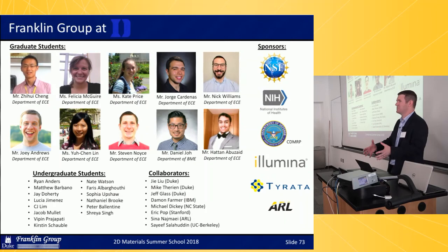And we're realistic enough in silicon to say, you know what, our devices are so small now, we can't dope the channel anymore, because 10 to the 18 dopant concentration would be 3 atoms in my channel, and I can't control that. And so now they're intrinsic. I think there's a lot of realism there that we need to think about with 2D materials. Is it even practical to talk about doping chemically when you're talking about devices that are used for scaling size? Because the number of dopant atoms would be so few.